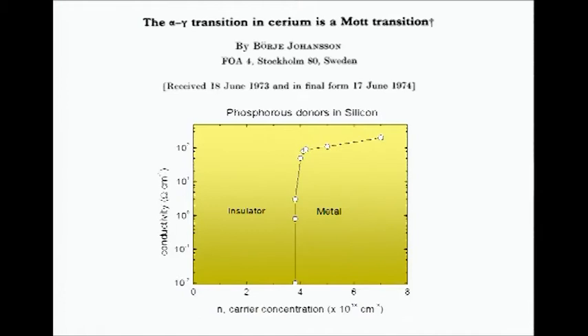You can see here that in phosphorus doped silicon, you can get a transition over to the metal once you dope in enough carriers where the wave functions overlap. So it's quite transportable - it's not just for cerium.